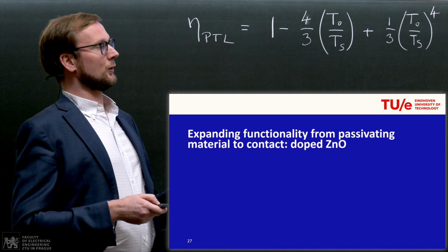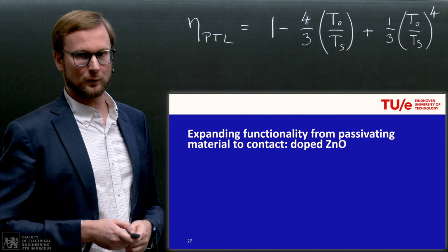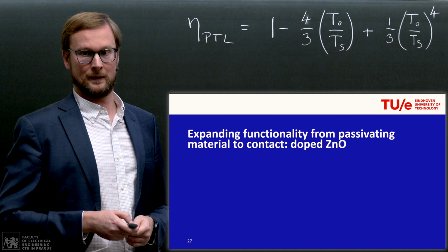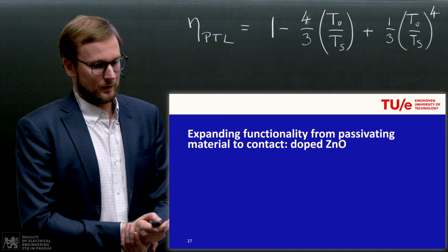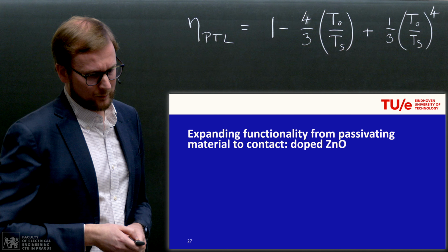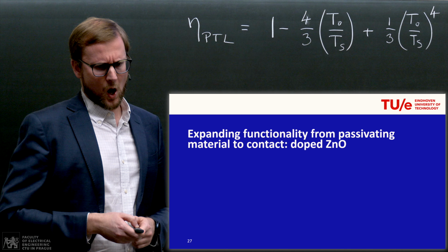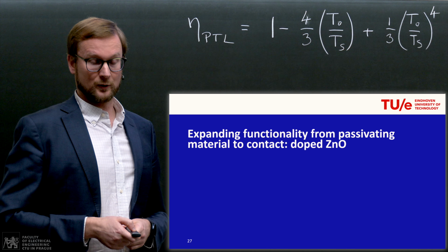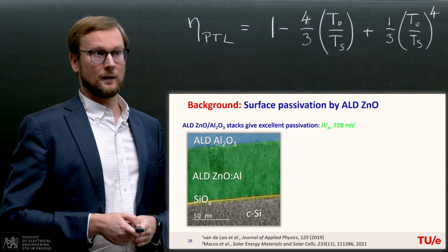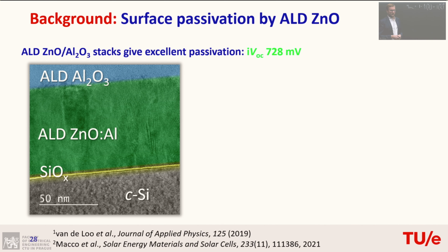And now, of course, this is not a contact stack, really. So it would also be nice to look at passivating materials that can also conduct current. And a choice that was made here, is actually doped a zinc oxide. A doped zinc oxide is a transparent conductive oxide, so we know that it is already conductive. It's used as a TCO in many kinds of thin film devices. And one of my ex-colleagues, Bas van de Loo, here in this paper demonstrated when we tried to put this on crystalline silicon, also an ALD process for the zinc oxide, that it actually gave very good passivation.